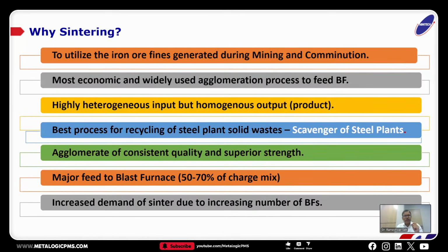Now, moving on to the slides, why is sintering done? Sintering is nothing new, and the sinter industry is a very established process, more than 100 years old, and it has got a fresh lease of life time and again. If you look at the mining of iron ore, because of mechanized mining, we generate almost 65 to 70% fines. By fines of iron ore we mean less than 10 millimeters. So these kinds of materials cannot be directly charged into the blast furnaces.